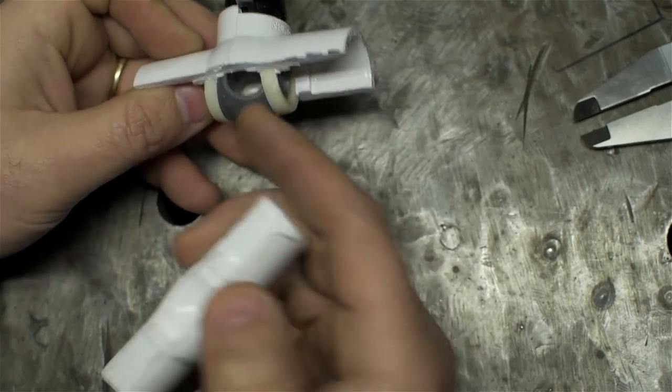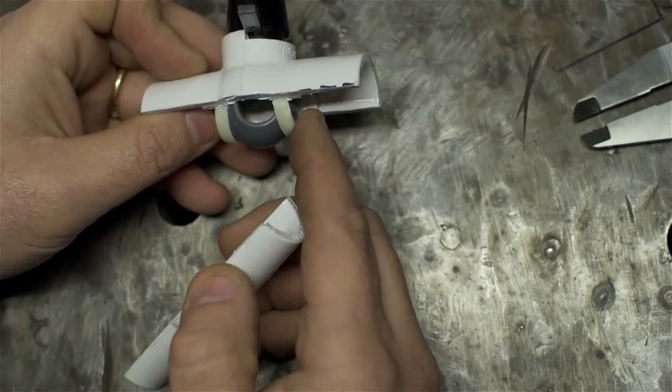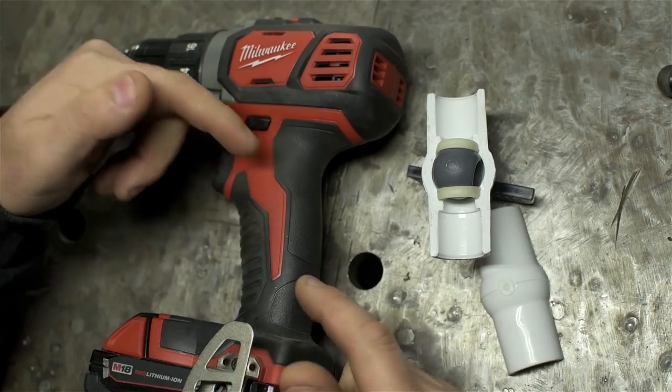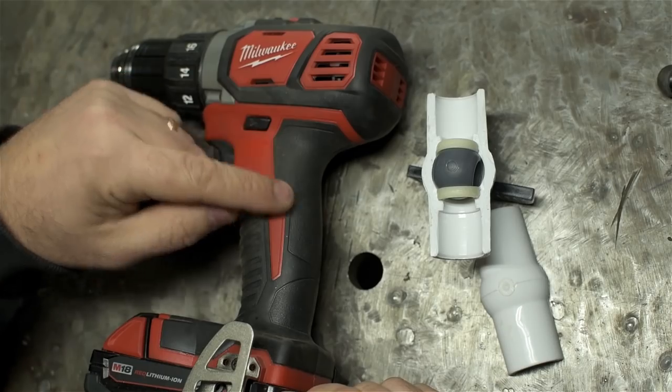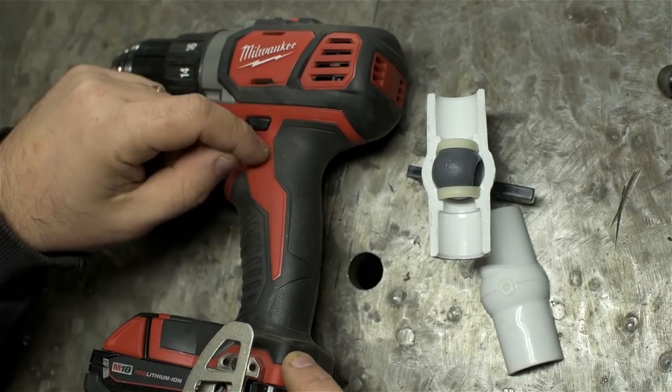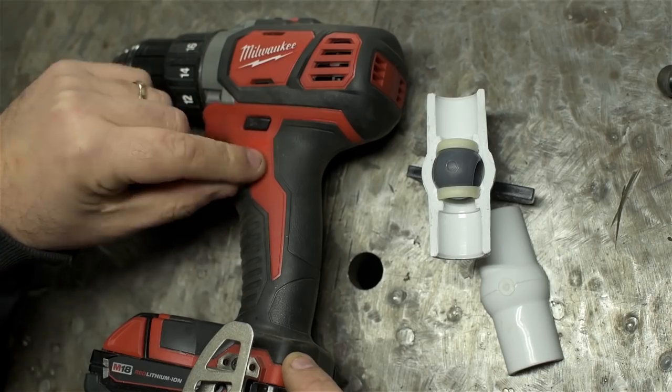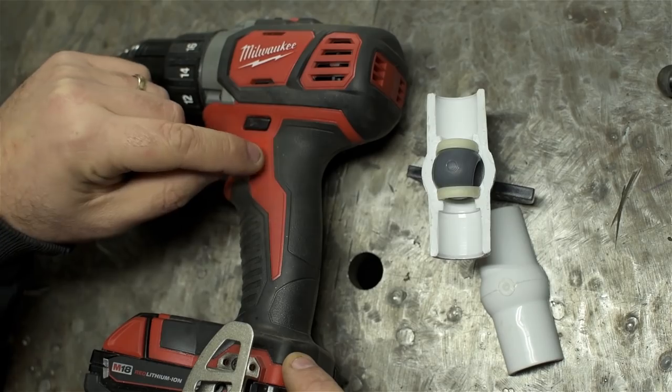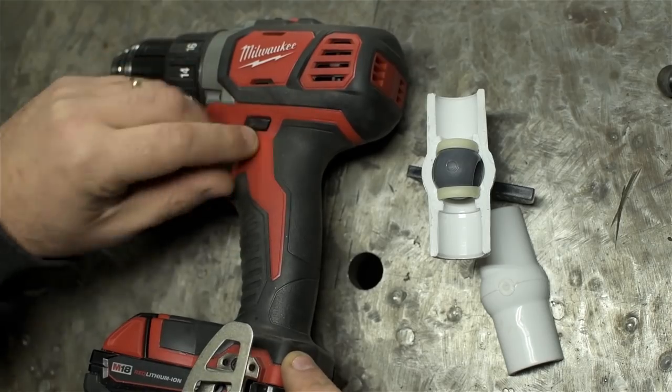Now, I can't imagine this sort of stuff is easy to figure out, but in a way, it's sort of the opposite of overmolding. I think we're all familiar with these rubber grips they put on everything these days. This would have been done in two steps, just like the ball valve. They made this red, rigid plastic part, put it in another tool that had just the voids for this overmolded part, and squirted the rubber in. Now, in this case, the rubber is selected so it's chemically compatible with sort of whatever base resin this is. When it goes in there hot, it sticks to this plastic, and it's hopefully never going to come off again. In the case of the valve, it's just the opposite. The materials here were selected so they were very incompatible. Now, I don't know what this ball is made out of. We could probably take some educated guesses. But if this PVC would have bonded chemically with whatever material that is, well, you wouldn't be in the valve business for very long. Let's put it that way.